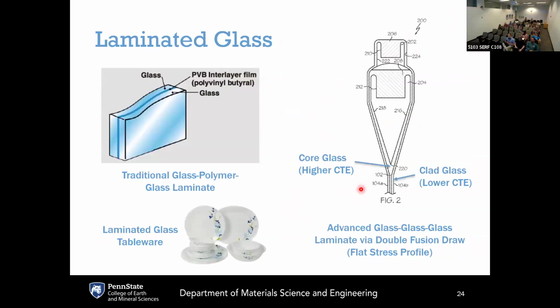Very quickly, another approach for improving the strength is through laminated glass. The most common way of doing this would be like in an automotive windshield, where you've got a polymer layer in between two glass layers. But another common way is actually a glass laminate. You probably have some of these dishes at home, these Corelle dishes. These are just laminated glasses. So there's an interior glass, which is white, and this is coated by a very thin, clear glass layer.